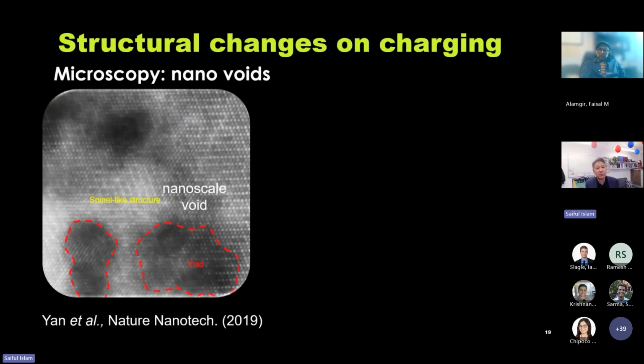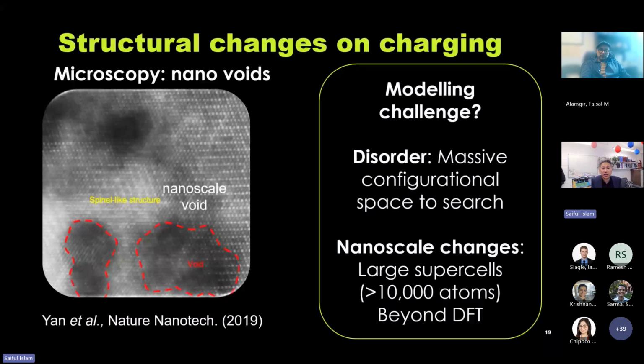There's also evidence from microscopy that there is some nanoscale void formation. So as you take out lithium, you're getting quite significant lithium cation vacancy clusters or nanovoids shown in this microscopy data here. But this presents a modeling challenge. There's a large degree of disorder, so there's a massive configurational space to search. For those nanostructural changes, we've got to model large supercells greater than 10,000 atoms. So that is well beyond classical DFT simulation. We need to go beyond current techniques.